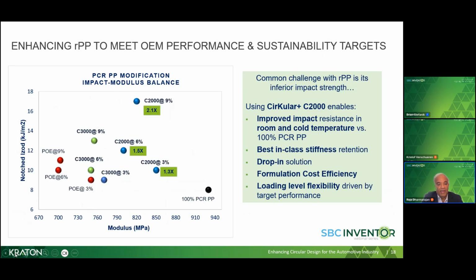So in this slide, we compounded our CirKular+ grades at different modifier levels into a PCR-PP. And we measured various properties, notably notched Izod and stiffness. As you can see here, with about 3% addition of C2000, we are able to increase the notched Izod at room temperature by a factor of 1.3. And it further goes up to a factor of 1.5 when we add 6% of C2000. We see similar enhancement with our C3000 grade as well.